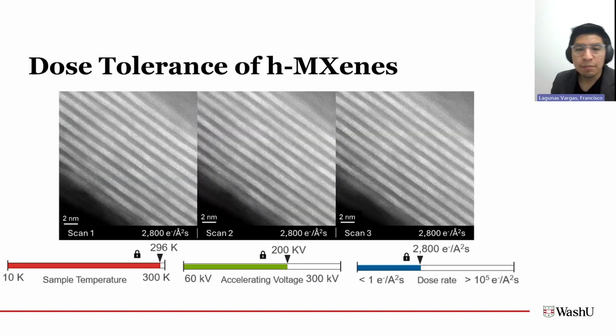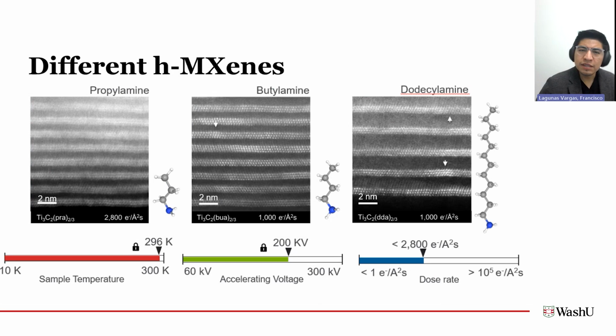So we played around with these materials a little bit more, and we found that if we were to image them at around 2,800 electrons per angstrom squared, we don't really see many effects upon subsequent scans. So you can see here I have scan 1, 2, and 3. And for the most part, these all look very similar. So using that, we defined our working range for these different MXenes at room temperature. And we started looking at MXenes with a variety of different surface group terminations.